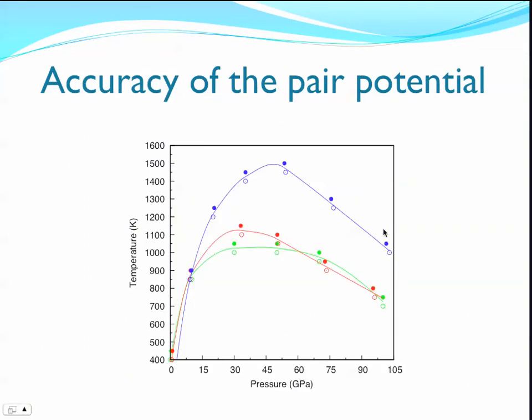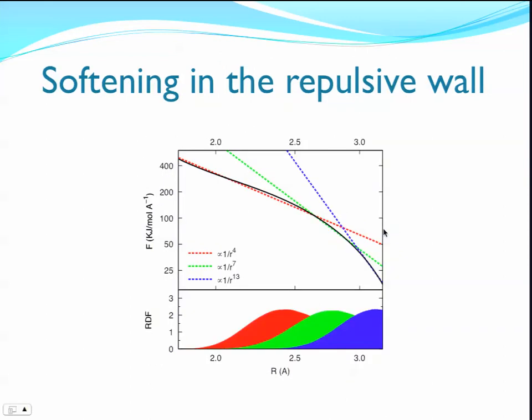And that's when we start seeing the anomalous behavior. Here I have three curves. One is obtained from neural networks, another is obtained from this Khaliullin pair potential, full potential, and this one is obtained from the short-range repulsion potential that partially includes the oscillatory term. So it becomes clear that this short-range potential is actually responsible for anomalous melting.